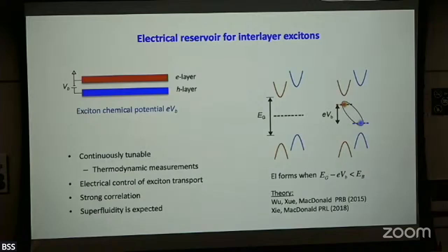How do we make sure of that? Experimentally, we can increase the separation between the layers, because tunneling is an exponential function of it. And we also make sure that this layer and that layer are misaligned in terms of crystal orientation, which makes it even harder to tunnel. So you can measure it directly.